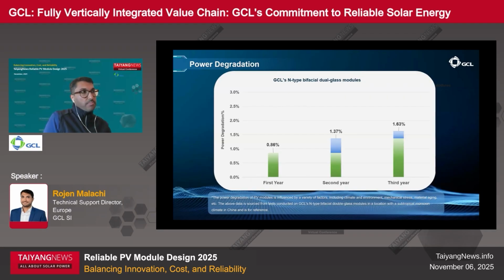Here we show the percentage of cumulative power degradation over 3 years. We have a first-year warranty of 1% and a yearly degradation of 0.4% after that. In this case, you can see our first year is 0.86%, the second year is 1.37%, and the third year is 1.63%. All of this is far below what we guarantee. So with this, we want to show that our modules can consistently deliver annual degradation below those guaranteed in GCL's limited warranty statement, and therefore supporting long-term yield predictability.